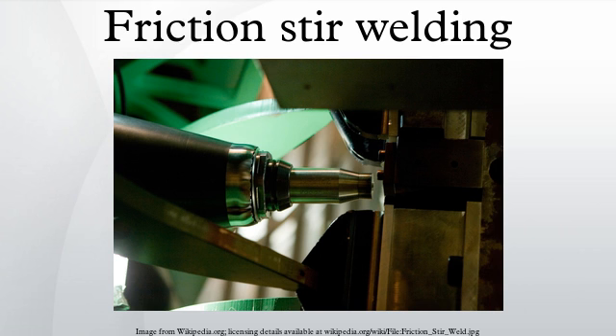A major difficulty in applying these equations is determining suitable values for the friction coefficient or the interfacial shear stress. The conditions under the tool are both extreme and very difficult to measure. To date, these parameters have been used as fitting parameters, where the model works back from measured thermal data to obtain a reasonable simulated thermal field. While this approach is useful for creating process models to predict, for example, residual stresses, it is less useful for providing insights into the process itself.